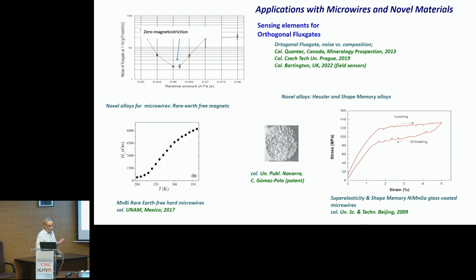You know the best material for hard magnetic material is neodymium iron boron, but the working temperature cannot go above 200 degrees centigrade, even that is high. So in these very particular cases, this type of alloy can be used. We have also been able to fabricate Heusler and shape memory alloys. Example here with nickel manganese gallium glass-coated microwires, where we had some visiting person from China.